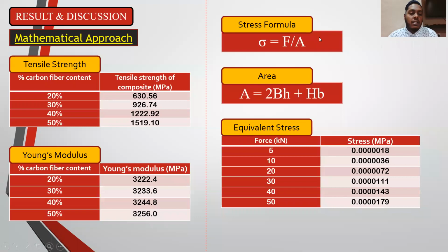And for the result and discussion in terms of the mathematical approach, we can see that when the carbon fiber content in the composition is 50%, the tensile strength is high, at 1519 megapascal. And also for the Young modulus, the higher the carbon fiber content, the higher the Young modulus. And the stress is also calculated, where the stress is higher when the applied force is higher, and this stress will be compared to the ansys simulation stress result.